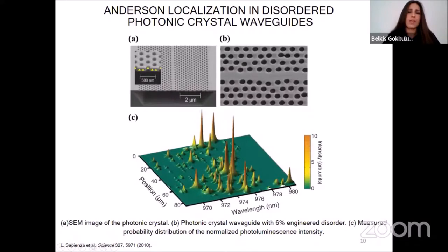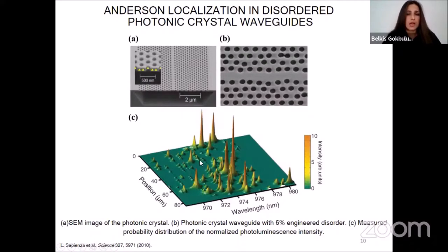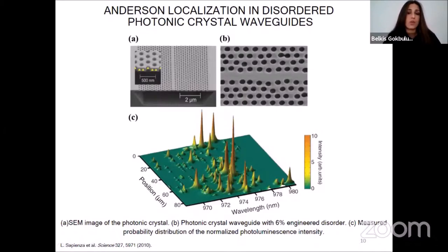Similar results from Anderson localized modes were also obtained by disordered photonic crystal waveguide structures, as seen in these two figures. Strongly localized Anderson modes were generated by adding extra disorder to a well-designed photonic crystal cavity structure. As the strongly localized Anderson peaks appear at random spectral and spatial positions, the spontaneous emission rate of the quantum emitter was demonstrated to be enhanced by a factor of 15 on resonance with the specific Anderson localized modes in this study.